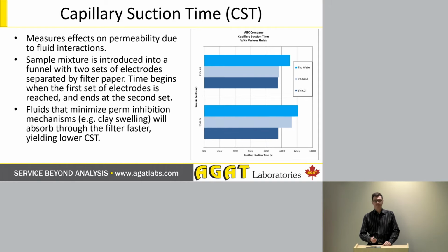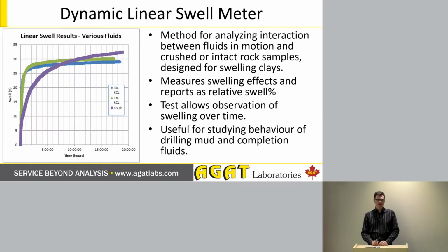fluids to have used. And lastly, the dynamic linear swell meter. This is simply a method for measuring physically how much a sample will swell when exposed to different fluids. In the example here, we're actually looking at, again, the same distribution of NaCl, KCl, and clean water, pure water. And we can actually see that although pure water had the worst response, it actually had a slower response as well than the other two.